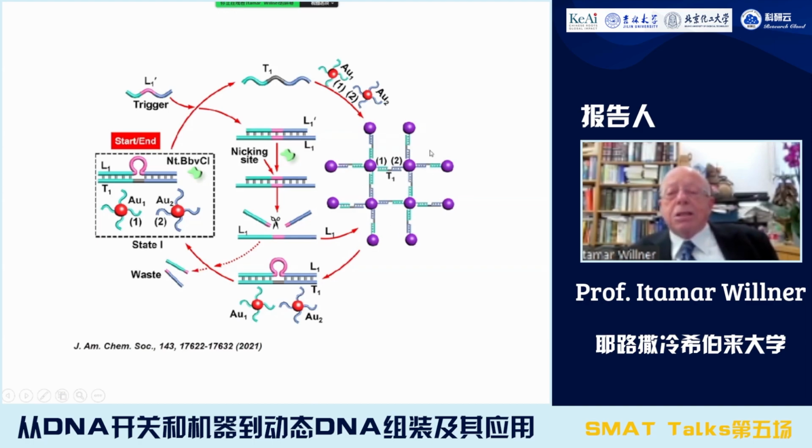T bridges the nucleic acid functionalized gold nanoparticles and induces aggregation of the particles. Aggregation of the particles is accompanied by spectral changes as a result of the interparticle coupled plasmon excitation process. But we engineer the strand L1' in such a way that it is cleaved by the nicking enzyme. The nicking enzyme cleaves this strand, and the released L1 displaces the bridging unit T1 to restore the original system.